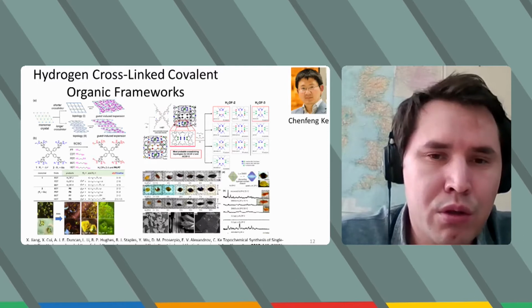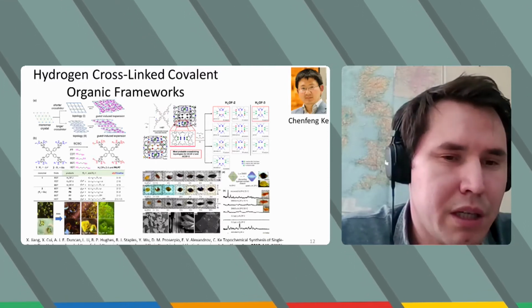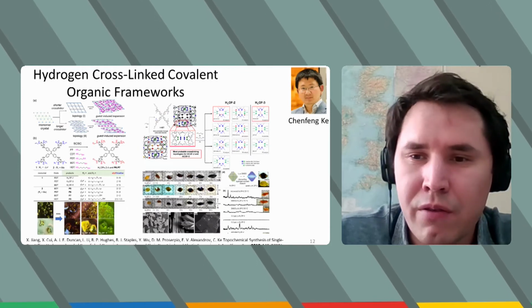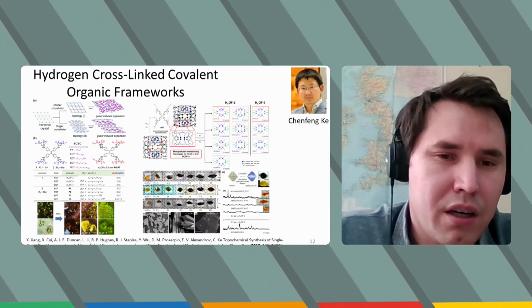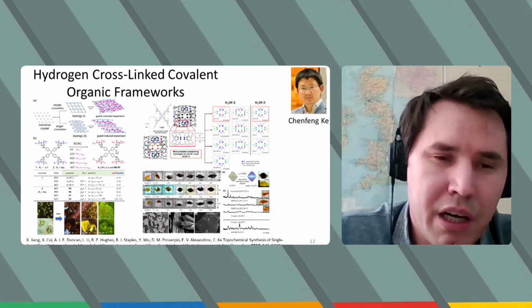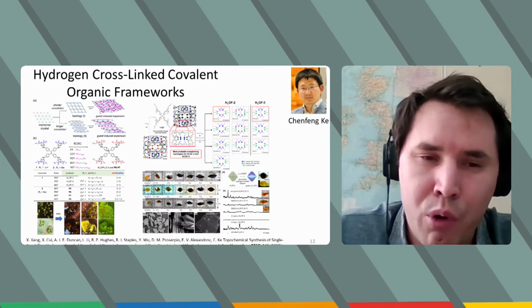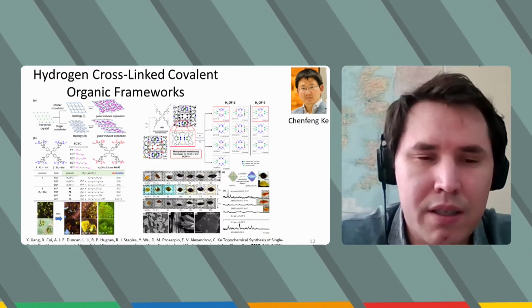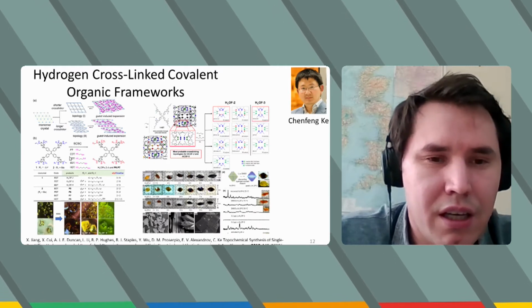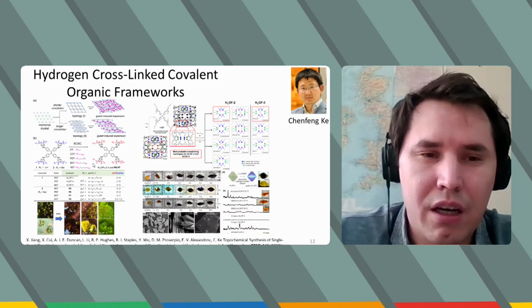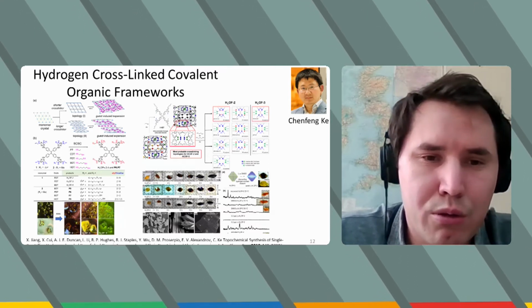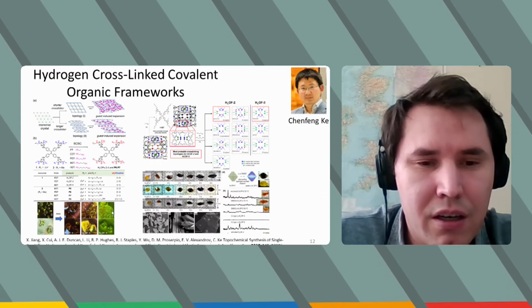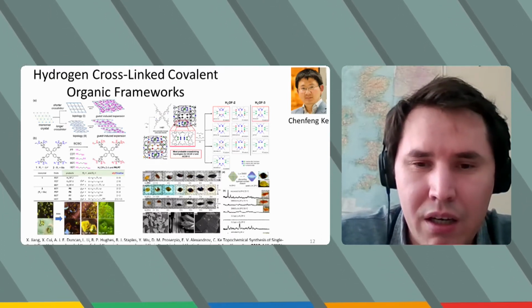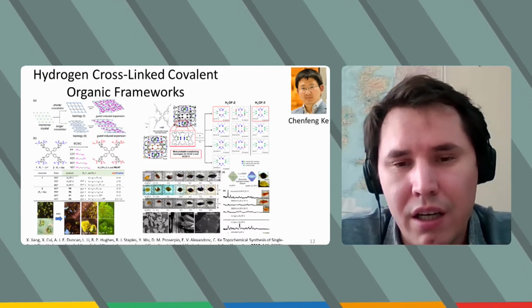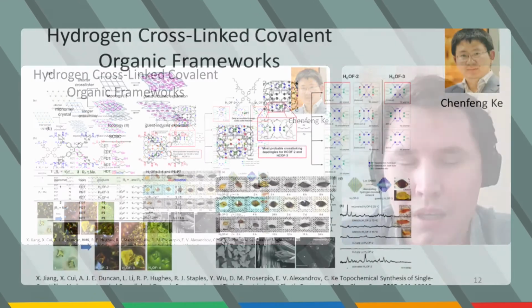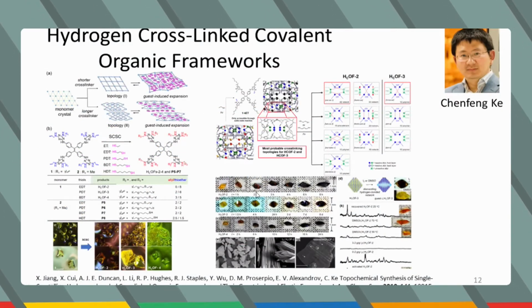Finally, I would like to show you new compounds which were produced in a very peculiar way. Professor Chenfeng Ke was able to synthesize crystals which are organic and connected by hydrogen bonds, but these crystals are porous. And inside of pores, they put additional linkers, and after polymerization under ultraviolet, it was possible to produce new crystals. And these crystals look like rubber because they can absorb, for example, iodine and increase their volume 6 times. This is, I think, quite impressive, and these crystals are very beautiful.